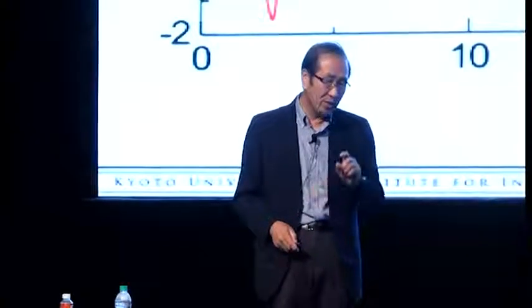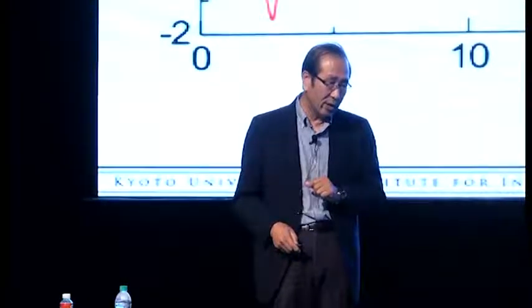So this is NMR, and at the liquid state, of course, the phosphate shows a very sharp line because it is isotropic, like this. And we can determine the structure of the glassy state. It's an amorphous state, and using the RDF and PDF, the pair distribution functions, that means we still have correlations, but the big issue is like this. Around 6 angstrom, the structure is maintained, but we cannot have long range order, of course. This is the amorphous state.